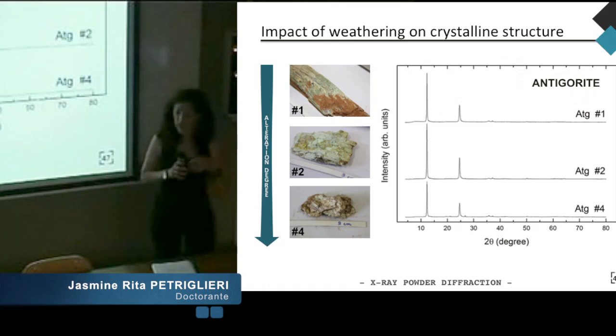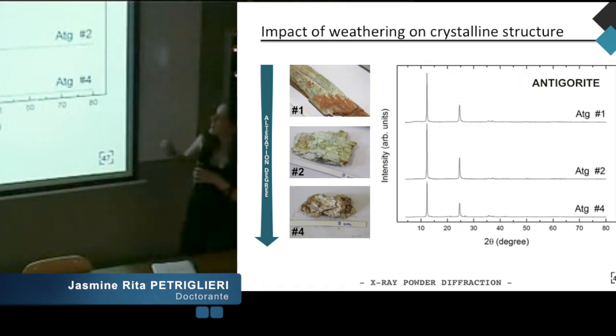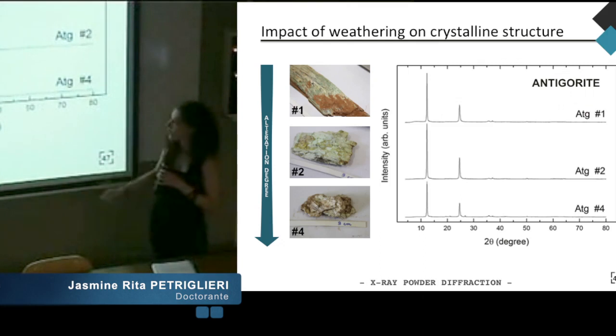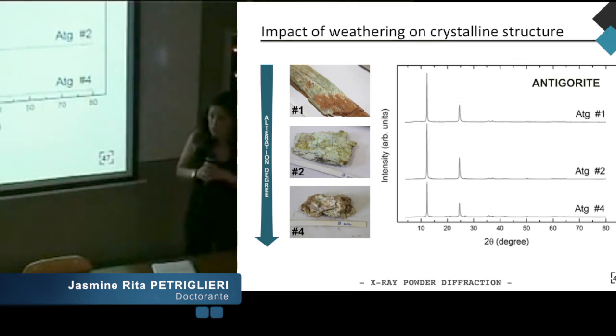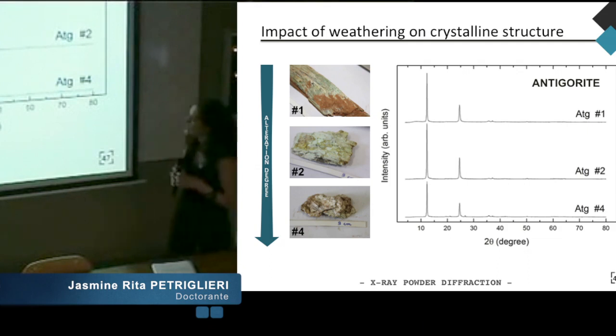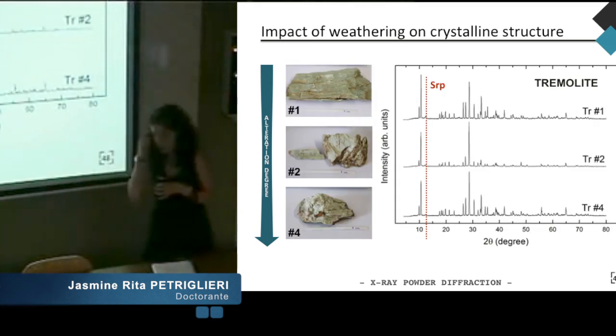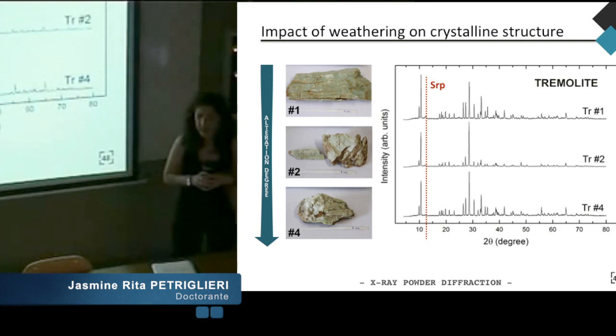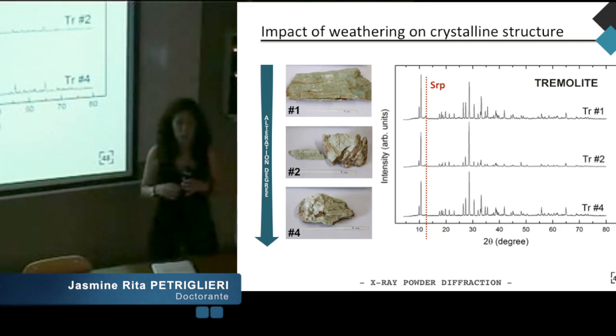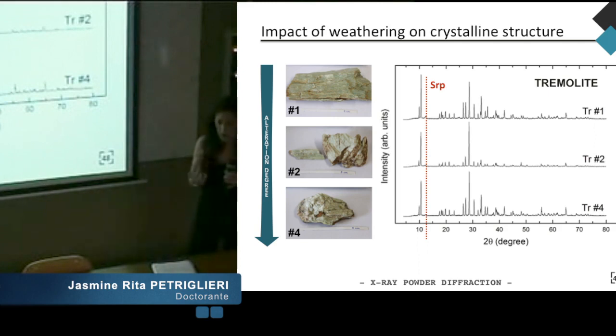As clearly evident in the slide, increasing the degree of alteration from one to four for the antigorite samples, diffraction patterns are completely comparable. No modifications are observed in peak position, peak broadening, or intensity. This is true for both antigorite and tremolite samples, suggesting that weathering does not impact the crystalline structure — probably weathering impacts chemical reactions at the surface.